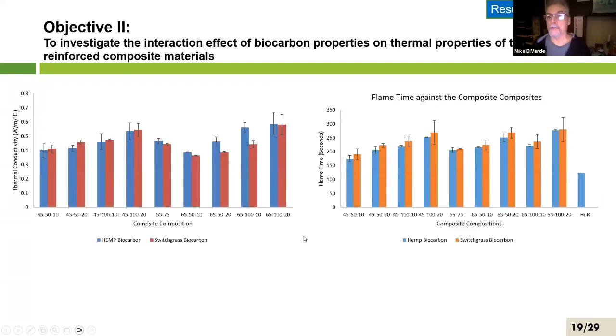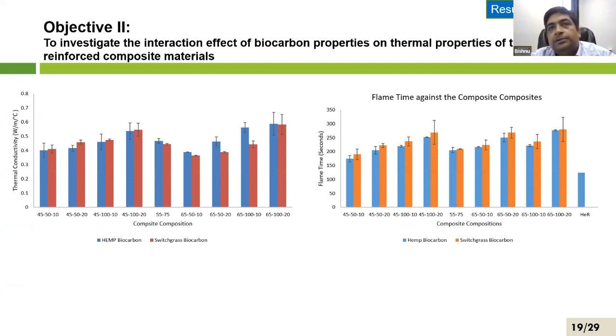Kind of important in cold zones like Saskatchewan, right? Yeah. So basically, because biochar is a very poor conductor of heat, and I think that's what we want to establish. By adding biochar, we can further reduce the conductivity, and that might be better for the construction work and all those things. There are other kinds of work being done where you further carbonize the biochar and look at that material for electrode application, where it will require higher electrical conductivity. But this biochar doesn't seem to have that. It just works as an insulation as we thought.